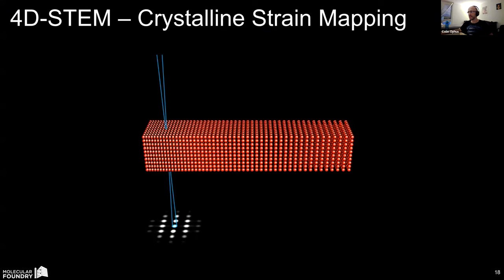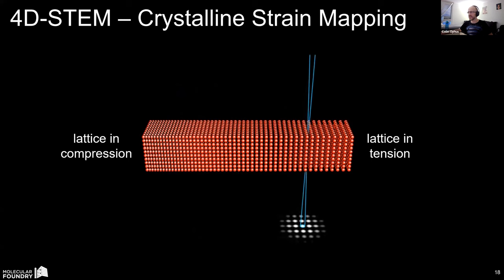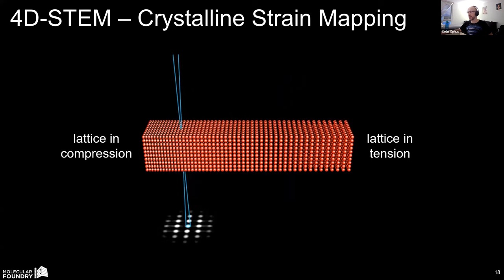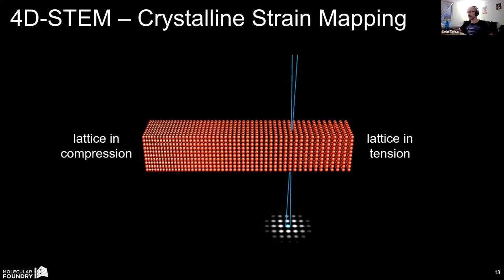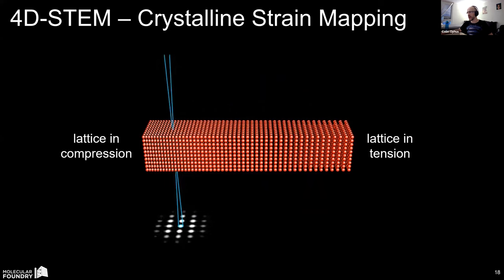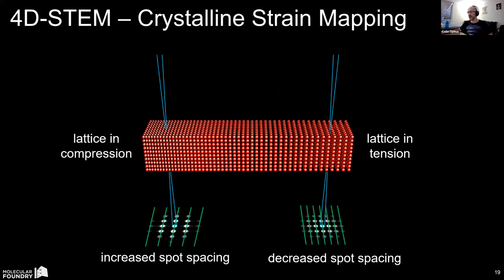The crystal strain mapping I mentioned, the principle is quite simple. If I look at a toy model where the lattice is in compression, atoms closer together on the left and further apart on the right, and I scan through it, you can see that the response is the spacing of these diffracted spots changes, and we're in reciprocal space. If the lattice atoms are closer together, we have further apart spots in Fourier space and vice versa. And so if we can make a high precision measurement of that spacing, we can measure the local deformation of the material.